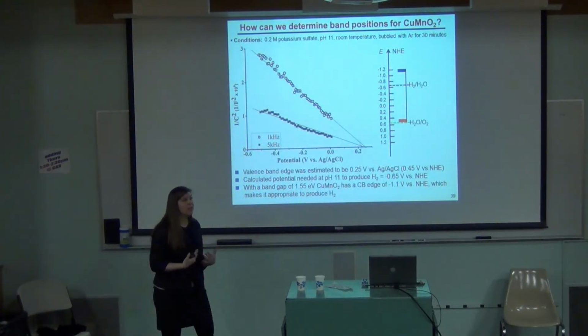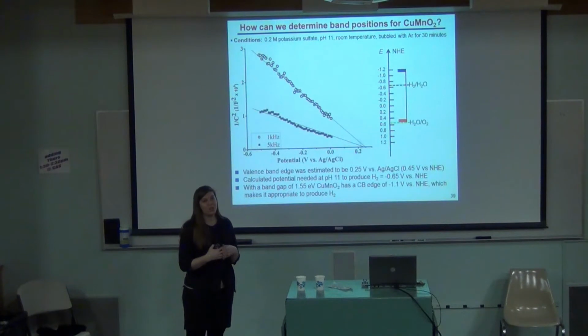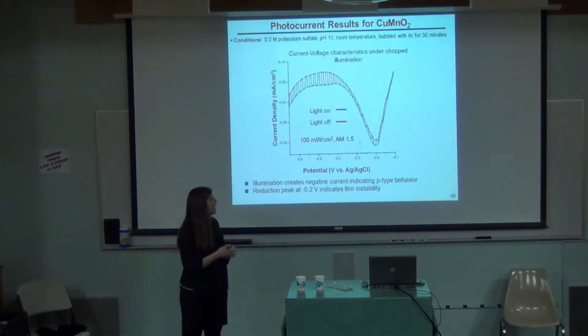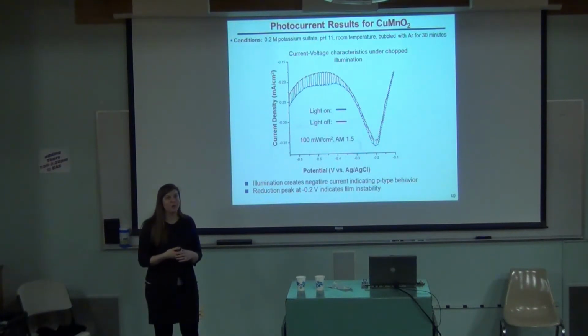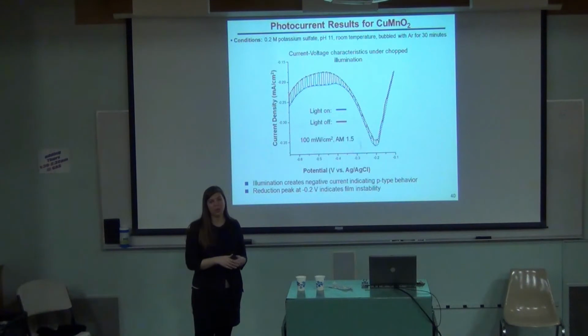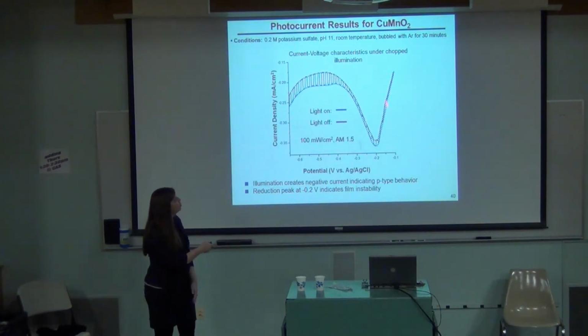So all of this was very encouraging, and you would think you're getting really excited for something earth-shattering, but unfortunately the earth-shattering result was that it reduces when you shine the sun on this material. So the material itself is just not stable in the sun. So it photo reduces. That's what this huge peak is here, is it's reducing itself.